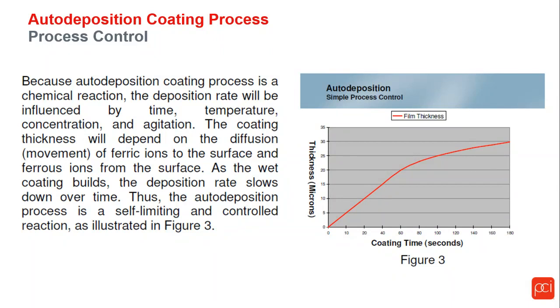As far as process controls go for the auto-deposition bath, it's controlled by time, temperature, concentration, and agitation. The graph to the side shows the limiting effects of the growth effects of the auto-deposition layer on the part surface. And it is self-limiting and a very controlled and consistent reaction.